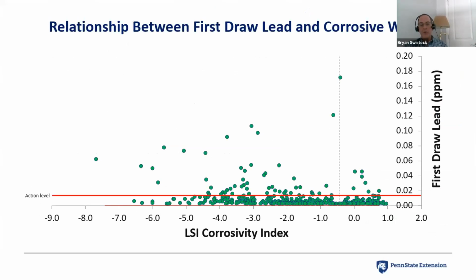When we look at relationships between things like the LSI index on the horizontal axis here and the amount of first draw lead, you see that the vast majority of the samples, first of all, are corrosive. Keep in mind, a corrosion index in this case of negative 0.5 or less is corrosive water. That vertical dotted line shows anything that's corrosive. Anything to the left of that is a corrosive water supply. You see the tremendous magnitude of samples that are corrosive to begin with. But you also notice that almost all the high lead concentrations are associated with that corrosive water, but not all. You do notice a few on the right-hand side of that dotted line.